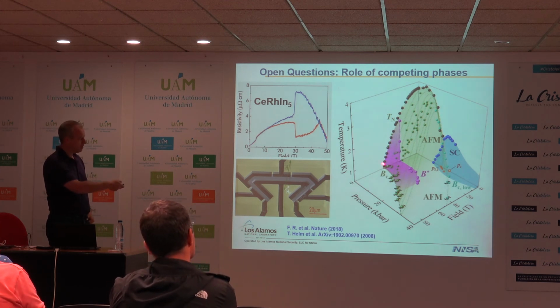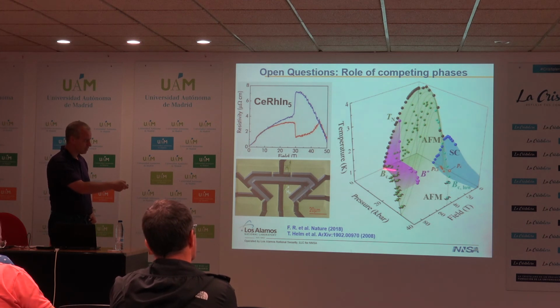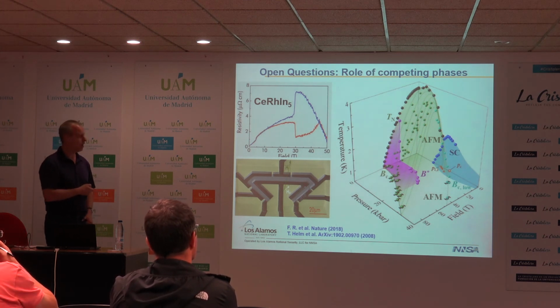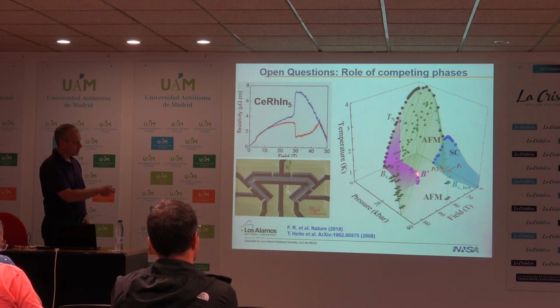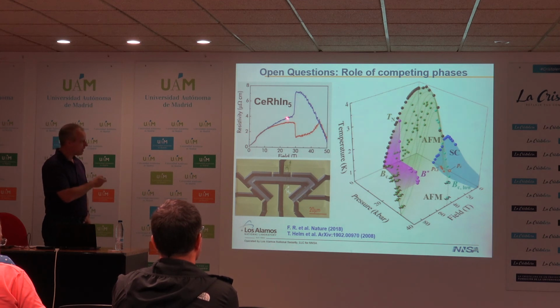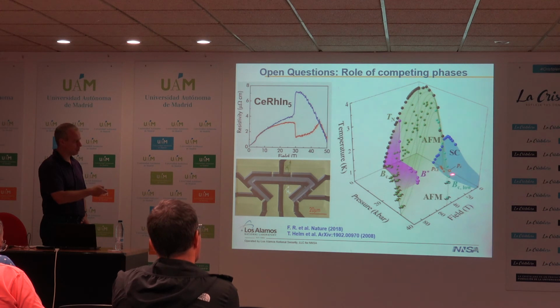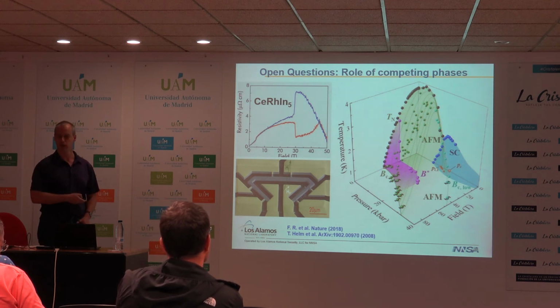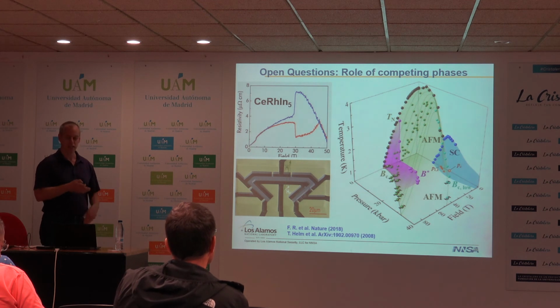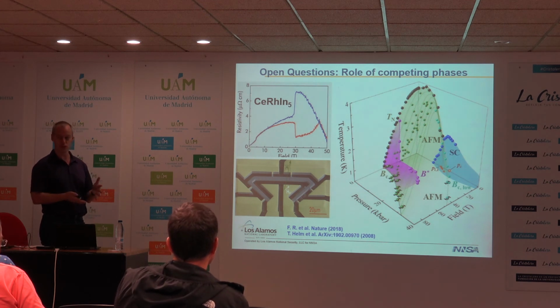In some ways the hope was that perhaps this nematicity would be tied to the superconductivity. But in fact, if anything, we see the onset of this nematic-like response increase as we're increasing pressure. So it goes to higher fields, maybe almost being repelled from the superconductivity, it looks like here. And the magnitude of this response shrinks with increasing pressure and essentially vanishes here. It's actually very close to the pressure at which the superconductivity has a maximum.